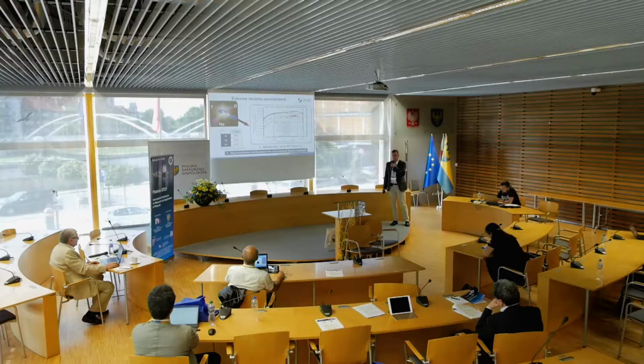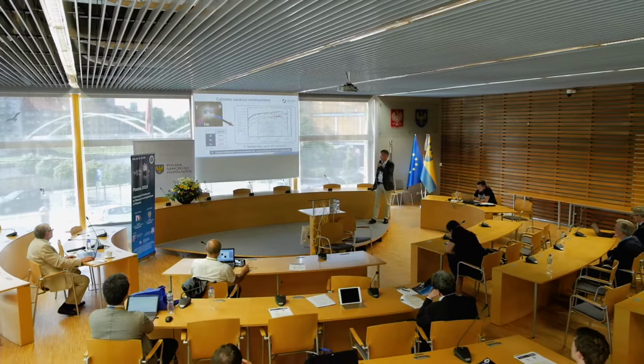The material is not only going to suffer from all these events caused by neutrons; as Tony mentioned in his introductory talk, it is going to undergo transmutation. So after 5 years of the first wall of ITER seeing these fluxes, we will not have pure tungsten as our first wall material. We will have only 94%, and the rest starts to be transmuted to rhenium, osmium and other subsequent isotopes, so it will create an unprecedented environment for conventional fusion materials.